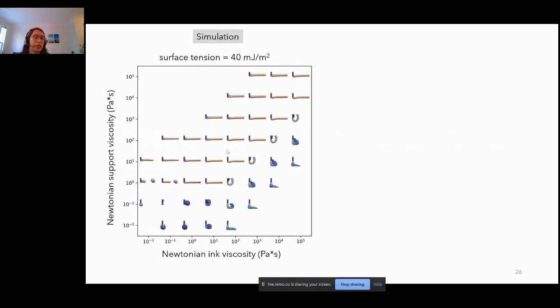So here we're simulating some filaments that are being extruded into a bath at a surface tension of 40 millijoules per meter squared, which is about what you would expect for oil and water. So you can see again, as you look down the diagonals at high viscosities, the viscosity ratio is what is controlling the filament shape here. But as you start to go towards lower support viscosities, we see a little bit of deviation, and we see filaments breaking up into droplets or just clinging to the nozzle as